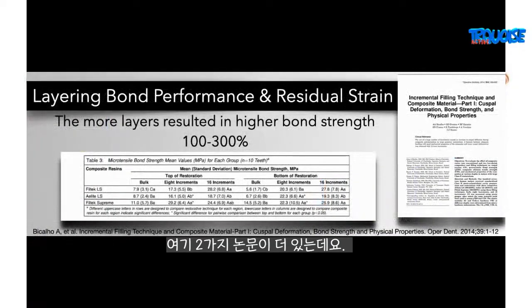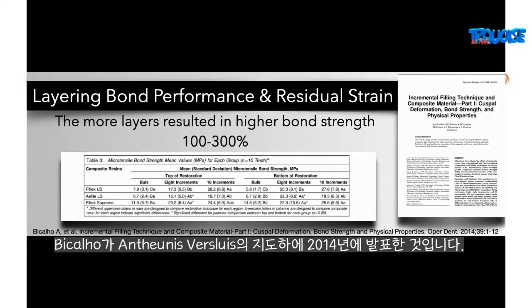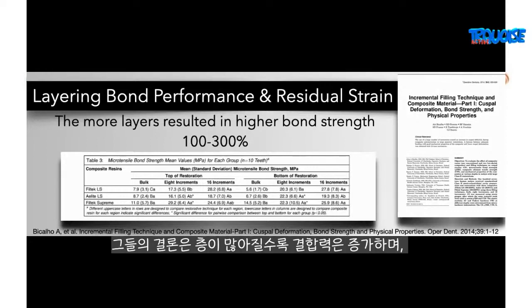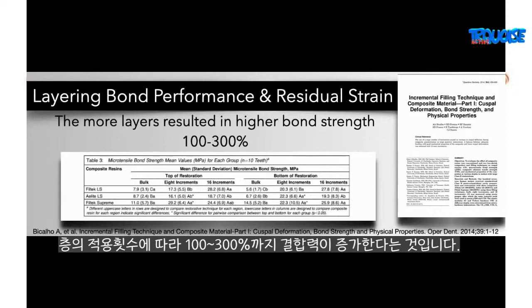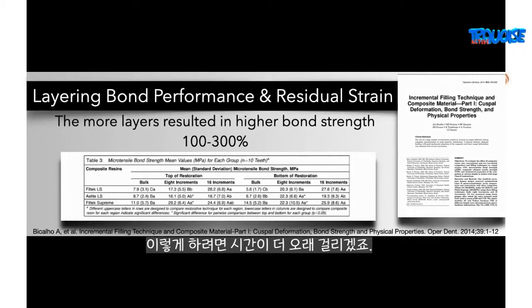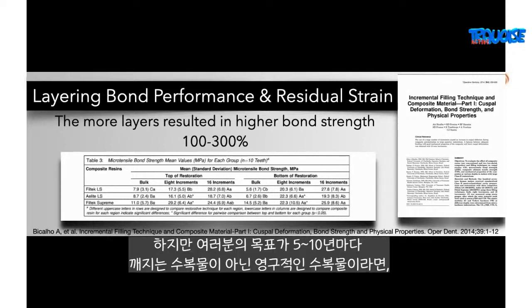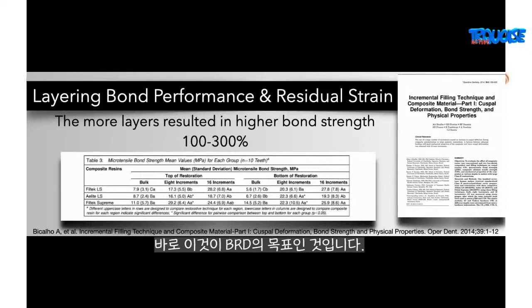And there are another 2 papers that were published in 2014 by Bicalho under the direction of Antheunis Versluis, and they came to the conclusion that more layers resulted in higher bond strengths, a 100 to 300% increase in bond strength, depending on the number of layers. Now, it takes more time to do this, but if your goal is to have a permanent restoration and not to have a restoration that breaks down every 5 to 10 years, then this is the goal of a biomimetic restoration.